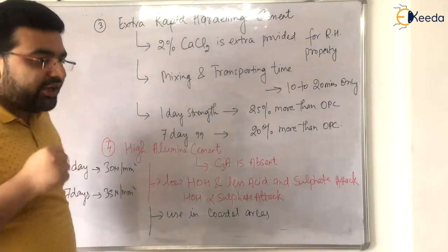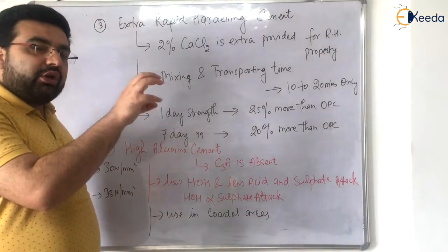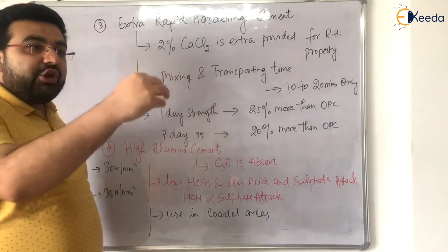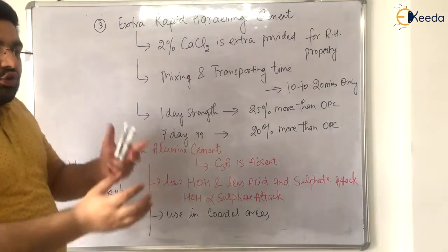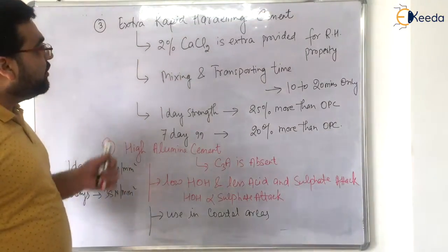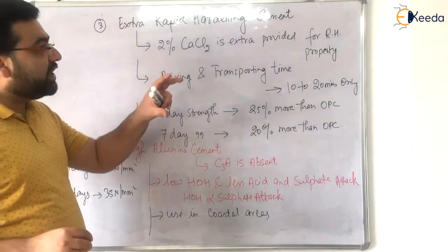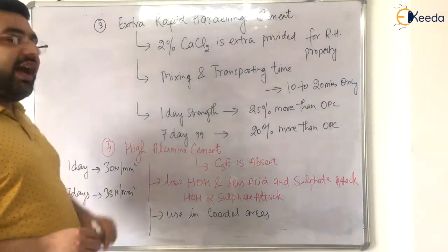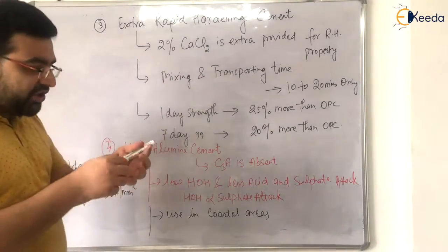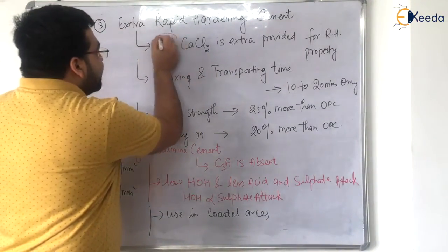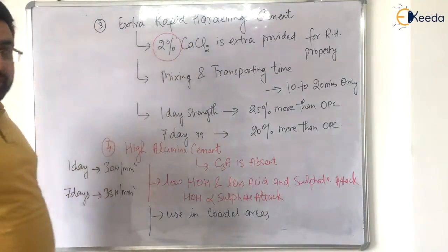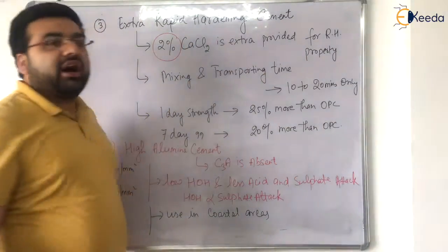But again, I have already told you, if you increase a particular constituent by some percentage, you have to decrease some other constituents, right? So to maintain the continuity, we do not increase the percentage of C3S much more, but we add some calcium chloride. How much calcium chloride is added? 2% of calcium chloride is added, extra, to provide the rapid hardening property.